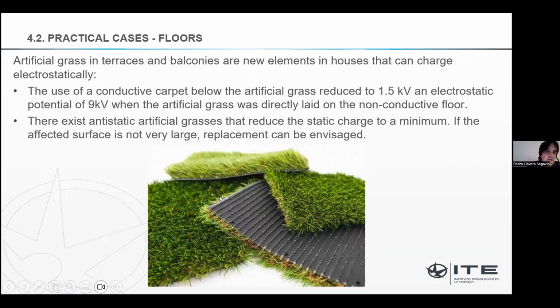The new problem is with artificial grass. It is being used more and more because it's nice. Of course, it's not anti-static. If you use a conductive carpet below, you can reduce it, as we measured. Artificial grass where walking you reach 9 kilovolts can be reduced to 1.5 kilovolts with a conductive mat below. But we are not sure that it works every time. It worked in one measurement we did. There are anti-static artificial grasses, but not very easy to find in the market either.